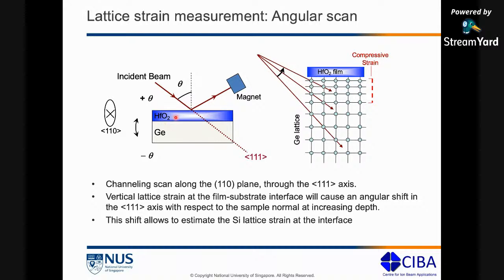So let's say we have this hafnium oxide film on a germanium lattice. The first thing we do is we have an incident beam. We align it to a channel. In this case, it's a 111 channel. So this is a perfectly channeled beam that goes along the 111 direction. We measure the spectrum. That's our first spectrum, the channeled spectrum. Then we start tilting the substrate in the positive theta direction and the negative theta direction. We go plus 0.2, plus 0.4, and then minus 0.2 and minus 0.4. So we have a total of 5 spectra that we collect.